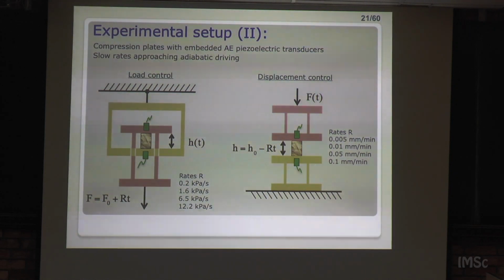What is the choice of the sensor? Why did you choose ultrasonic as a frequency in which you want to measure acoustic vibrations? Well, what you get spans more than ultrasonic. I will come to that now, but clearly there is a lot of interesting data between 200 kilohertz and 2 megahertz, 3 megahertz. And the setups are usually prepared for that. If you try to work on the audible range, first of all, you have more noise. And here it's easy to clean the noise. If you go to higher frequencies, there is also electrical noise that couples to the space. So the ultrasonic range is quite good for this. Clean measurement. Yes, to have a clean measurement. But you could go to a slightly lower frequency and still get the same, okay?